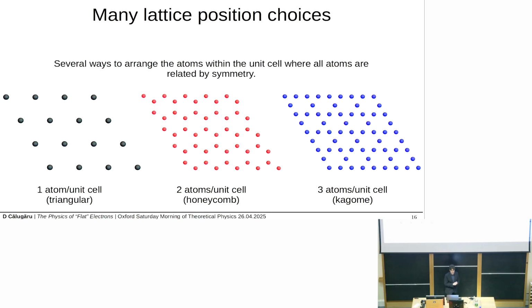So let's build some intuitive picture, right? You fix the space group, which are the symmetries of a crystal, but you're still not done, because there's a lot of freedom on how you place atoms within the unit cell. And that freedom matters. Take this example. All these 3 structures here share the same Bravais lattice. They're built on a triangular lattice, right? But depending on where you put the atoms, you can end up with a triangular lattice, a honeycomb lattice, or a Kagome lattice, each with different numbers of sites or occupied sites per unit cell and different symmetry properties.